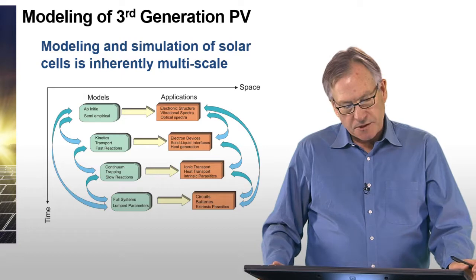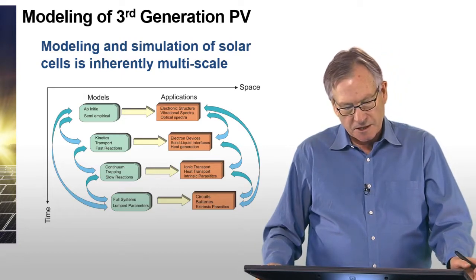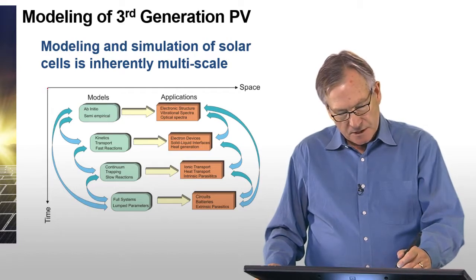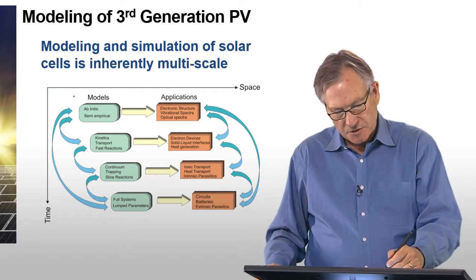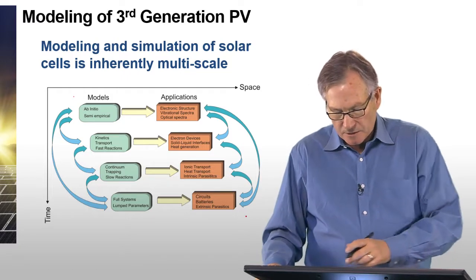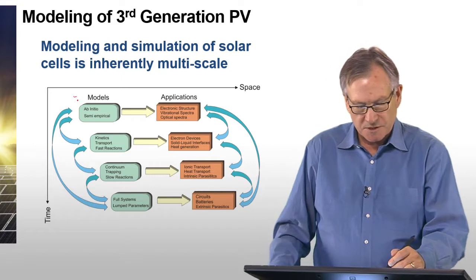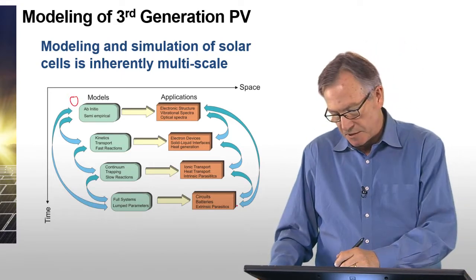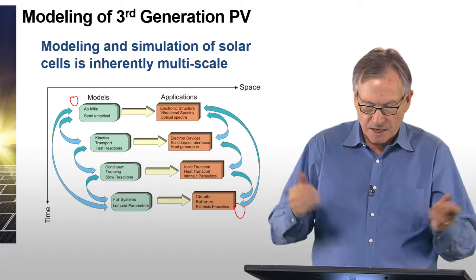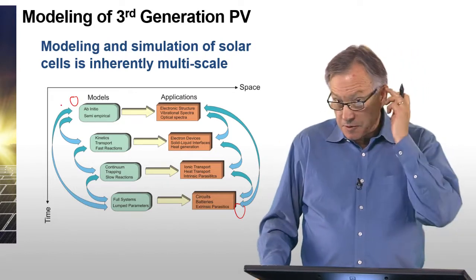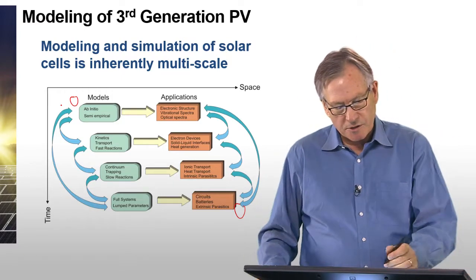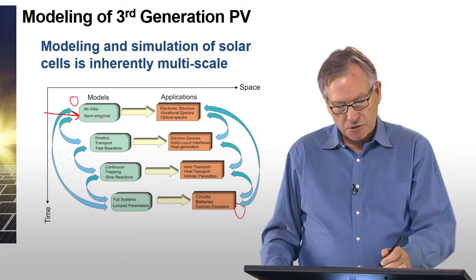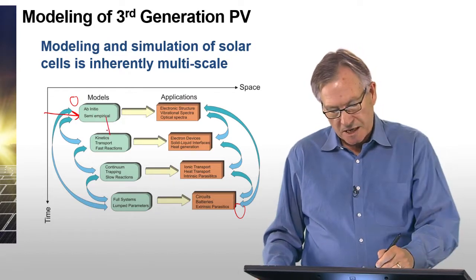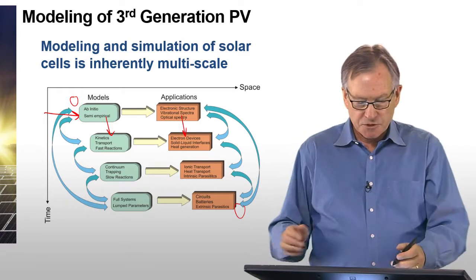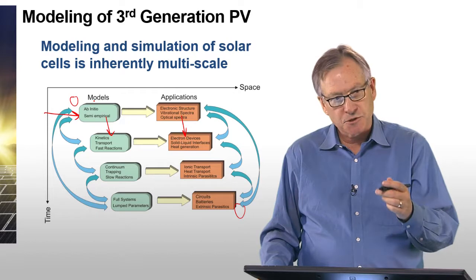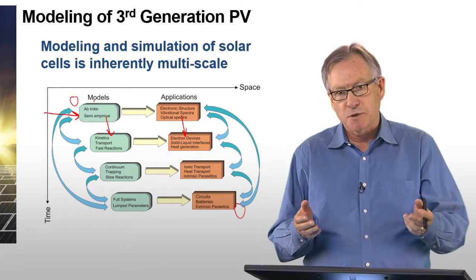And so basically the approach that one has to take is sort of illustrated in this chart, and that is that you have things with short time and spatial dimensions at this corner, and things at long time and large spatial scales at the other. And this basically corresponds down at this end to the molecular scale, and at this end to the system scale for devices. And so basically the typical approach that's used is multi-scale modeling, in which high fidelity physics models are used at this level, and then the information that you get from modeling is passed to the next level. That information is used, for example, for electronic structure, doing first principles electronic structure.